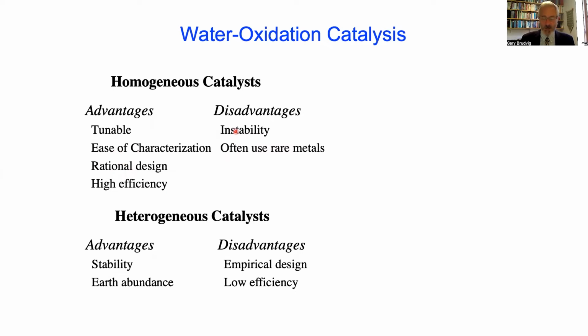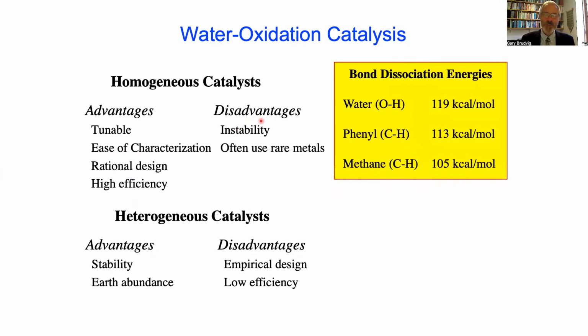I can highlight the instability by comparing the bond dissociation energies. The OH bond of water is stronger than any CH bond in an organic molecule. So if we have a molecular complex with such bonds, they're going to always be easier to oxidize than water. And this is in fact reflected by the fact that if we carry out the water oxidation reaction in solution, water oxidation catalysts do not last very long, and it's led to the conclusion that they're going to be unstable.